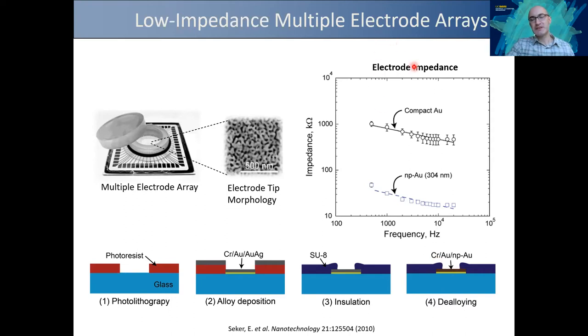If you measure the electrical impedance in artificial cerebrospinal fluid at 1 kilohertz, which is the characteristic frequency that we are most concerned with during electrophysiological recordings, we've seen a 25-fold reduction in the electrical impedance. So we were very excited about this, but this excitement is a materials science excitement that does not yet have a biological basis to it. So we had to see if this has biological relevance.